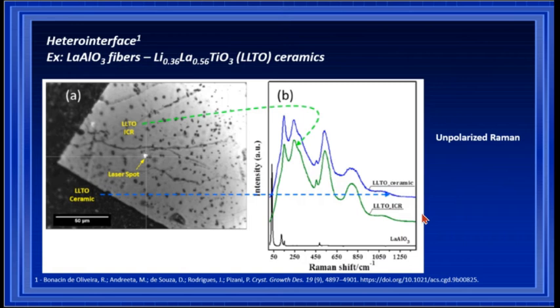In this way, we also analyze with Raman to see if we are getting the same structure as the ceramics, and when we compare the LLTO ceramics with the LLTO ICR, in this region, we can see we have the same structure. Of course, there are differences in the intensity of the bands because of the crystal orientation, but the structure is the same for unpolarized Raman.